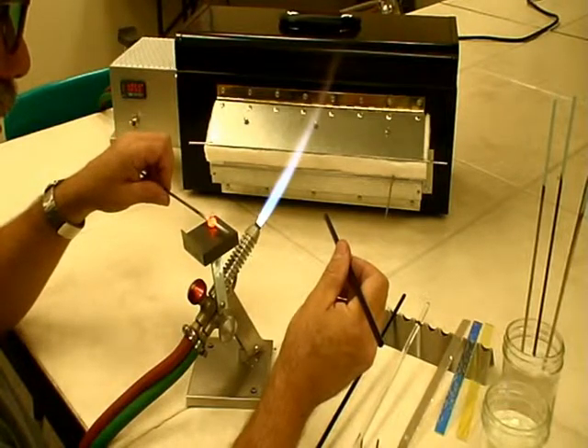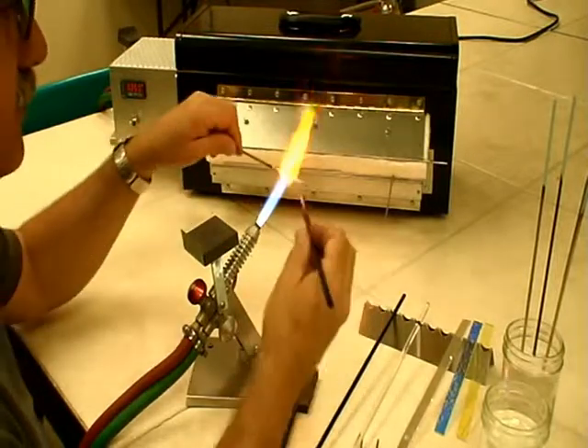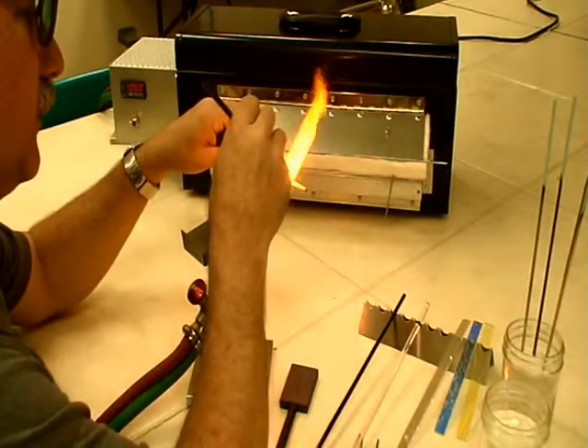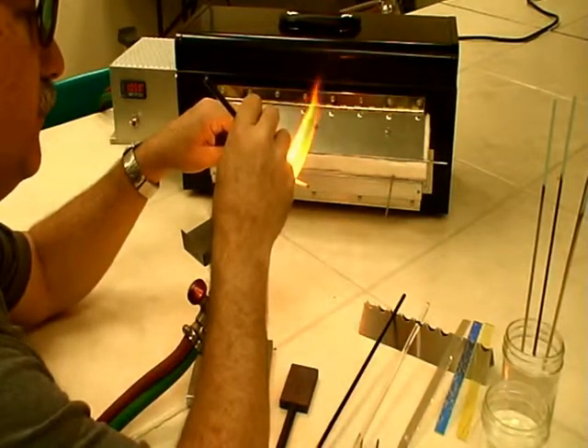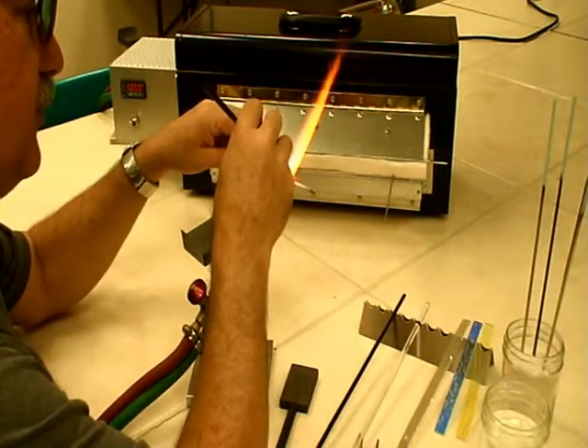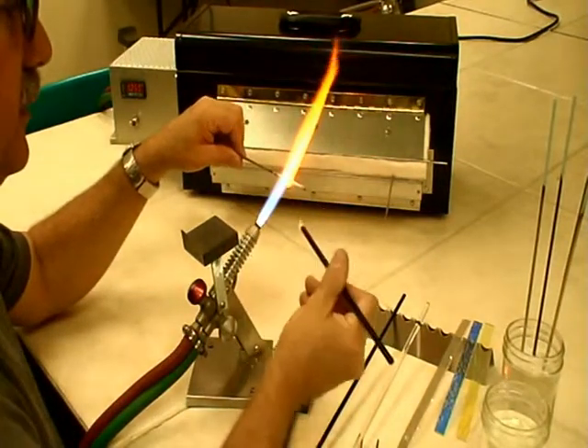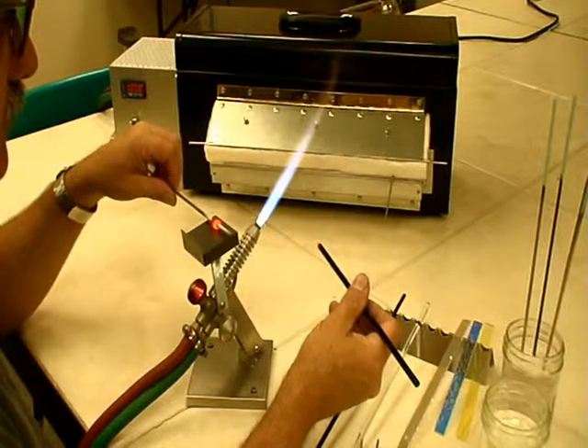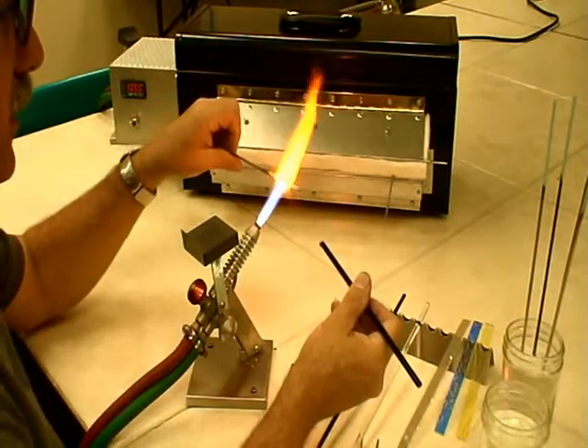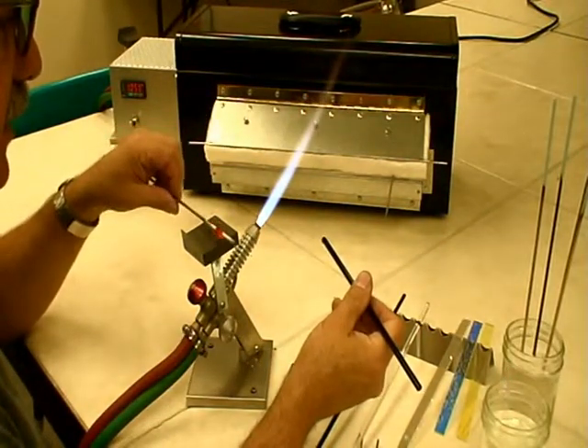Dichroic should be treated in much the same way as you would treat any other precious material. If you've worked before with gold or silver foil, you know that once you apply it to the bead, you have to be careful not to overheat the bead or you'll vaporize the material. So you work out in a cooler part of the flame, further out. And that's typically what you're going to do here with a dichroic. You want to treat it just like it's one of those precious metals. It is a thin coating. It is applied to the glass. And I think a lot of times people apply the glass like they would if they were putting it on with a glass rod. Need to take a little more caution. That's what we're going to do right now.